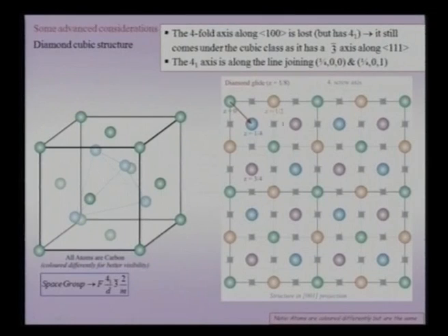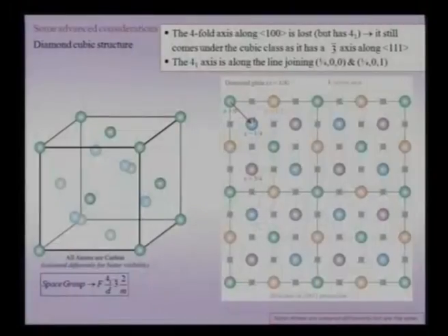So, these are 4 unit cells which I have shown here, wherein I have superimposed some of the screw axes in the structure, and you can see the screw axis does not pass through any of the atomic positions, it passes between the atomic positions, and the diamond glide connects an atom at z equal to 0 to the atom at z equal to 1/4. So actually the glide reflection plane is at z equal to 1/8. So it is located at 1/8 the height, and therefore it will move an atom at z equal to 0 to z equal to 1/4. And this vector shows only the direction of the diamond glide and not the glide plane itself.